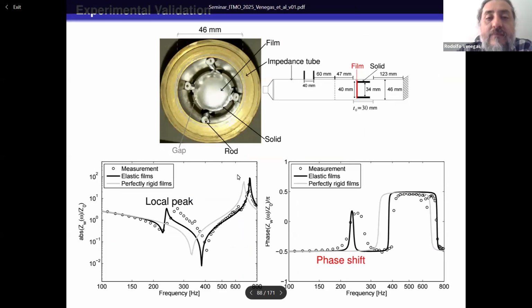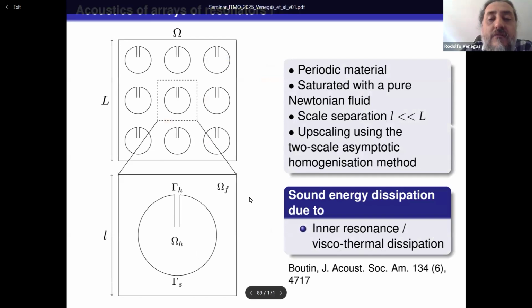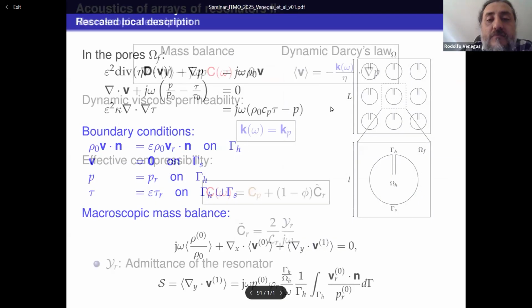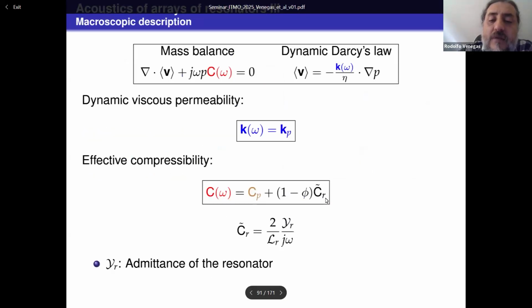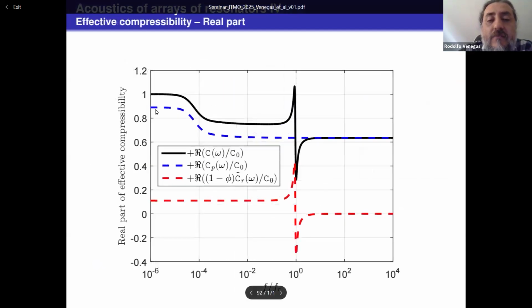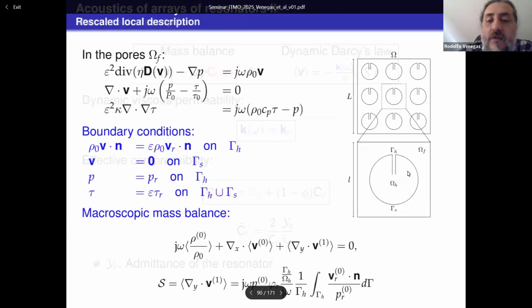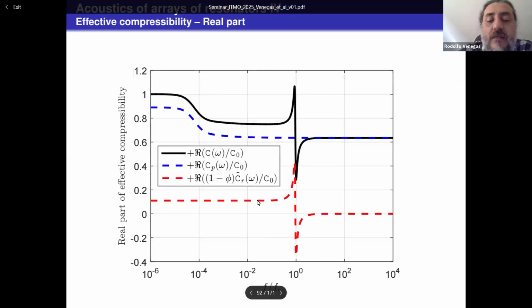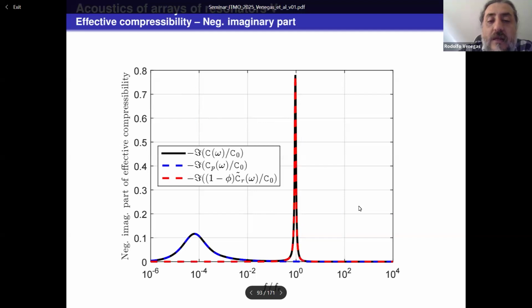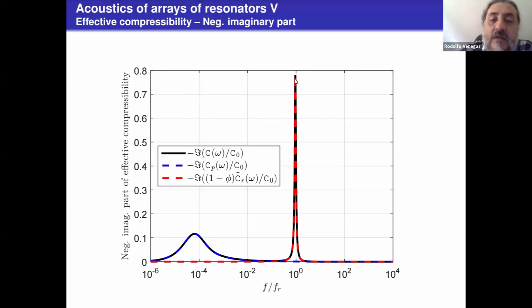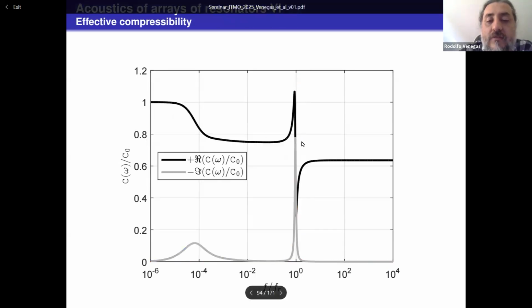For acoustics, with an array of acoustic resonators, we have an array of Helmholtz resonators. We apply homogenization, and we get that the compressibility is affected by the admittance of this acoustic resonator. In blue is the compressibility associated with what's around this resonator, and in red is the compressibility associated with the resonator itself. Black is the combination of both. In the imaginary part, we have a relatively large peak around the resonant frequency of the resonator, and this is the overall compressibility.